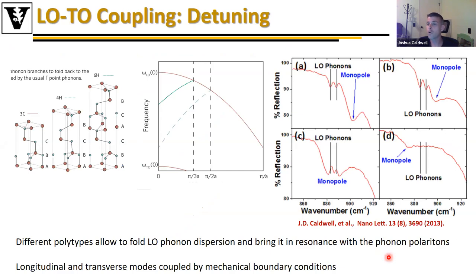So how can we start to control some of the spatial coherence of these modes? Well, it turns out there's actually some interesting phenomena that is, I'm not gonna say unique, but fairly unique to silicon carbide, in that if I look at silicon carbide crystal structures, you have the purely cubic structure, which is designated the 3C structure. But because of the broad variety of different stacking orders of the silicon and carbon atoms that can be thermodynamically stable, there's actually 210 known polytypes of silicon carbide that can be found or made. Two of the more predominant ones for power electronics are 4H and 6H.